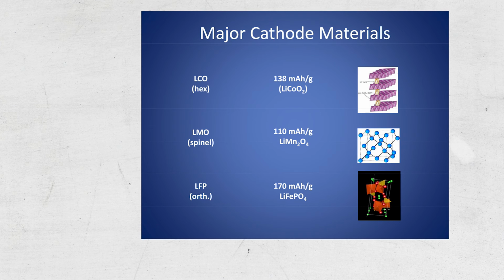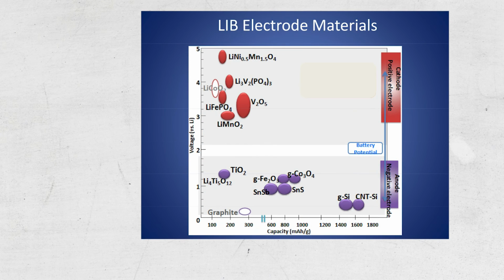There's a huge amount of work on providing new materials with improved characteristics. So this slide shows the scale of capacity, which is how much charge in coulombs or milliampere hours you can store per gram, and the voltage at which the system will work. For an anode, the voltage should be low, and for a cathode, the voltage should be high, all right? So ideally, a battery that has graphite as the anode and this material, the nickel manganese spinel, will provide you 4.5 volts, right? That's very high. So voltage is very important in the energy, of course. Energy density is the capacity times the voltage.